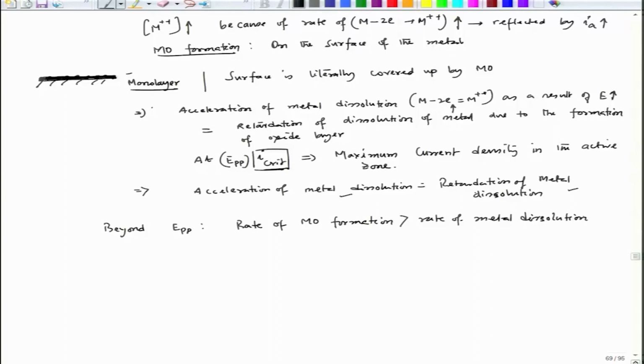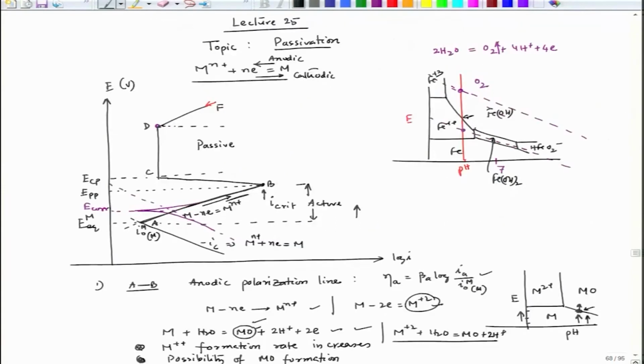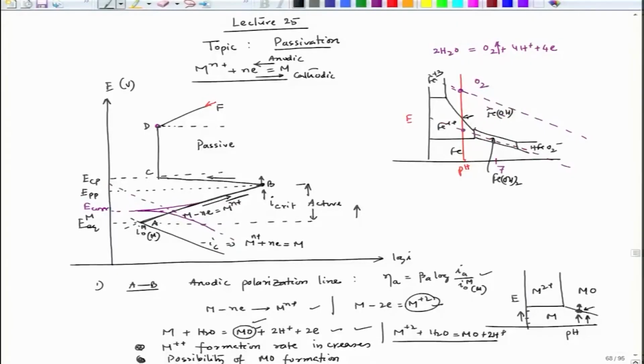Now, when we have this particular situation, then I will see that after reaching this, once we increase potential a little bit, since the metal layer is completely covered up by metal oxide, and the amount of metal oxide is also increasing, it will cover up the metal surface completely and the current density starts dropping, because now the dissolution of metal will be decided by